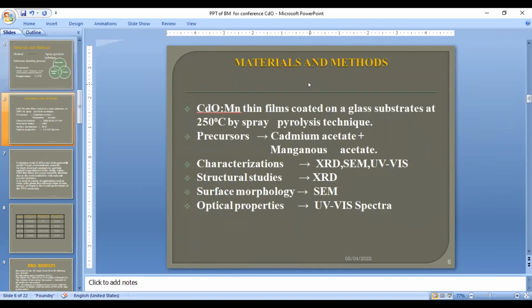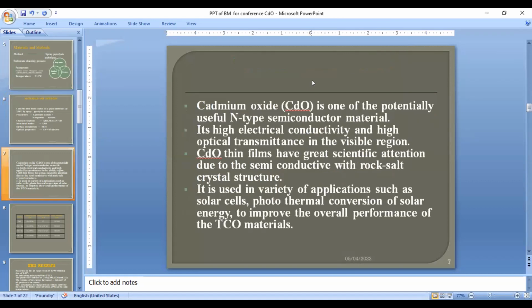So, materials and methods. The cadmium oxide films doped with manganese are coated on glass substrate at 250 degrees by spray pyrolysis technique. The precursors we used are cadmium acetate plus manganese acetate. The characterizations are XRD, SEM, and UV. The structural studies are done with XRD, the morphology with SEM, and the optical properties with UV and transmission spectra. So these are the things.